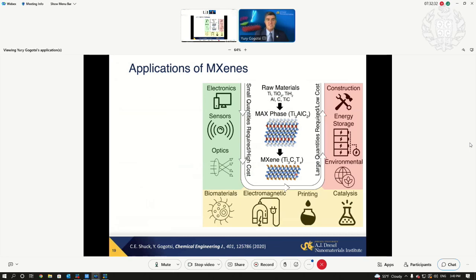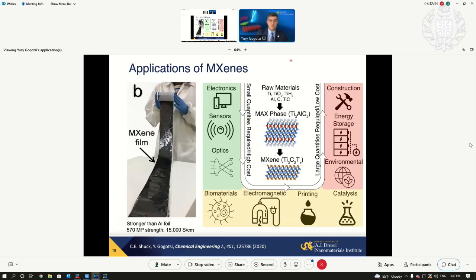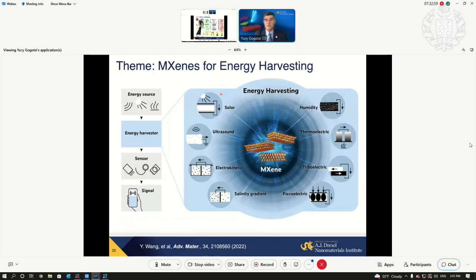What is important is that since we can make them in larger quantities, as I showed you, we can make them with extreme properties. For example, we can make a freestanding 1 micron film, and you cannot do it with metal. You cannot easily process metal foil, like aluminum, to that thickness. And they have the same strength as aluminum foil and high conductivity. With larger quantities, we can use them for environmental applications, not only for small electronics or sensors.